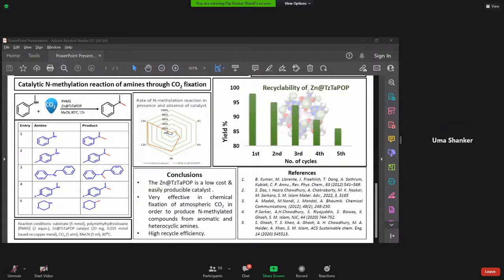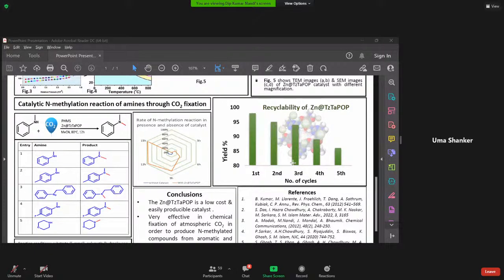Okay, I understand. My second query is, during the recyclability experiment, have you tested the stability of this material, Zn@TzTaPOP? How are you sure that its phase is not changing, or it is not degrading, or zinc is not leaching into your reaction medium? So have you checked? I tested the stability. You can see the yield is slightly decreasing, but that is okay. My point is, what is happening to the catalyst which you have used? Yes, I think that the pores inside the porous organic material get blocked somehow. Okay, but some evidence is required to confirm. Evidence is required, of course, but we did not emphasize that much.